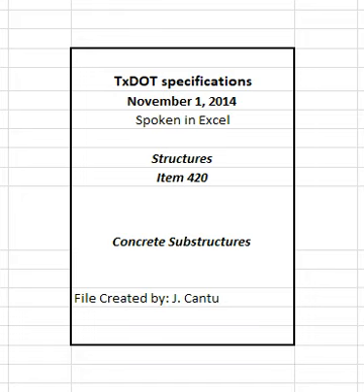4.7.8 Handling and placing. Minimize segregation of the concrete and displacement of the reinforcement when handling and placing concrete. Produce a uniform, dense compact mass. Ensure concrete free falls no more than 5 feet except in the case of drilled shafts, thin walls such as in culverts, or as allowed by other items. Remove any hardened concrete splatter ahead of the plastic concrete.